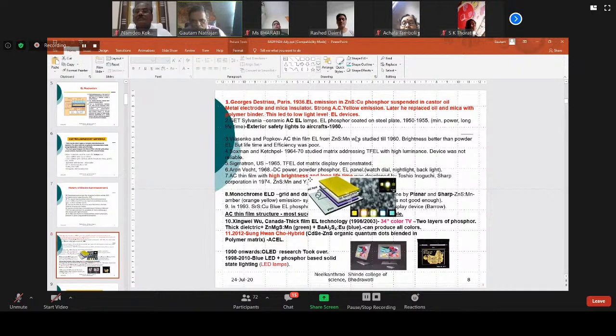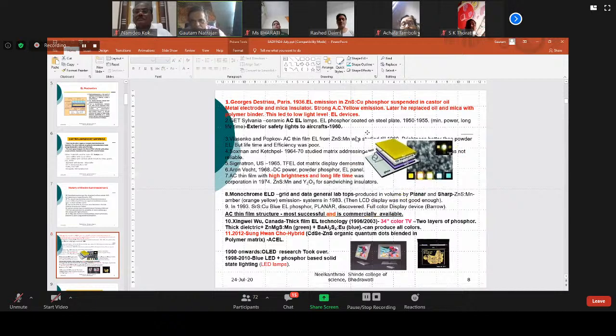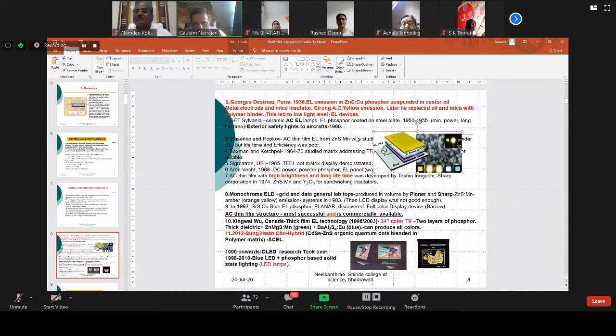Then Aron Vecht, mentioned in the earlier slide, prepared a DC powder phosphor EL panel for watch dial night shift backlight. This is 1966. Then AC thin film high brightness, long lifetime was developed. Inoguchi is the pioneer of current AC EL devices. Toshio Inoguchi, Sharp Corporation, 1974. He used zinc sulfide manganese as the electroluminescent phosphor and yttrium oxide as insulator.